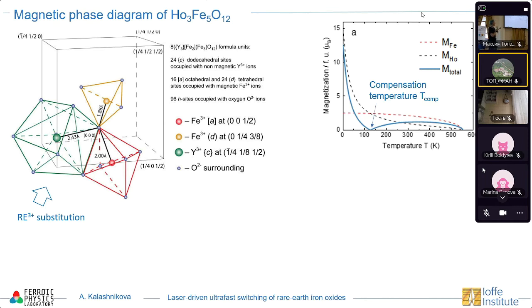In the iron garnet, there are two positions for iron. There are two magnetic sublattices. They are coupled antiferromagnetically, but there is an imbalance between the number of ions in these two positions. Therefore, these are usually ferrimagnets.